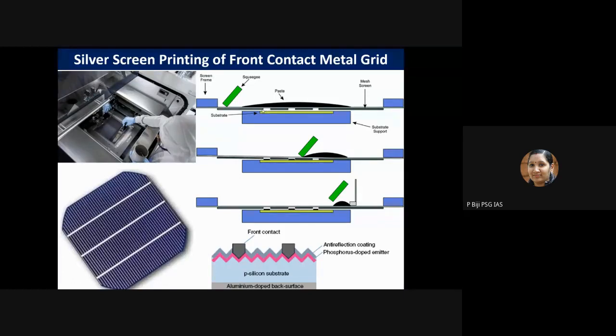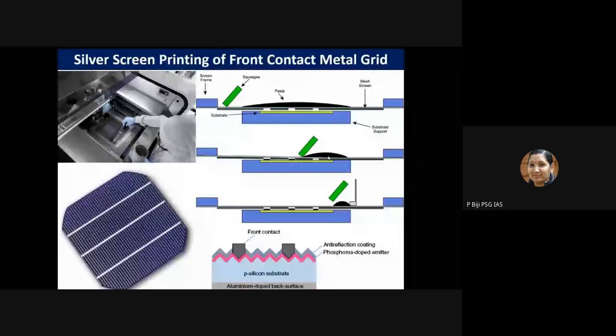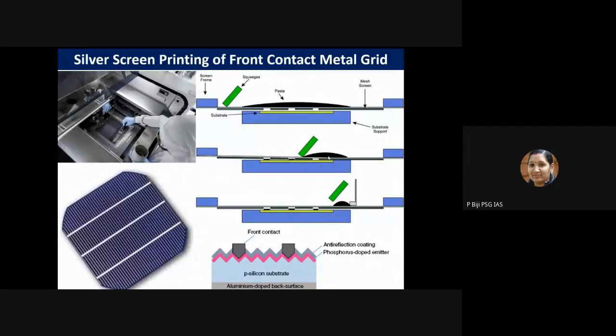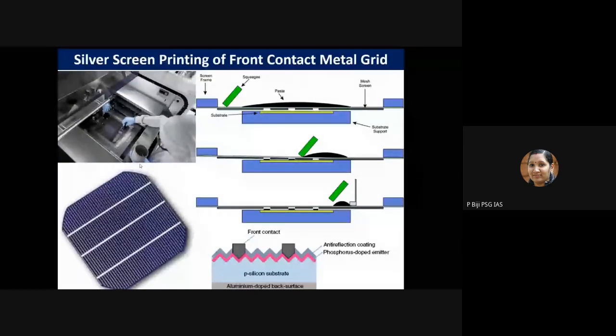Through these openings, the metal paste will be pushed onto the solar cell wafer. That's how you will get the patterns on the solar cell surface. Then the screen will be lifted out, and a drying process will occur, and after that one more sintering process will occur, which will assist in adhering these metal lines onto the emitter surface. So that's the screen printing process. This photograph shows the screen printed silver fingers as well as the bus bars printed through screen printing technology at commercial production scale.